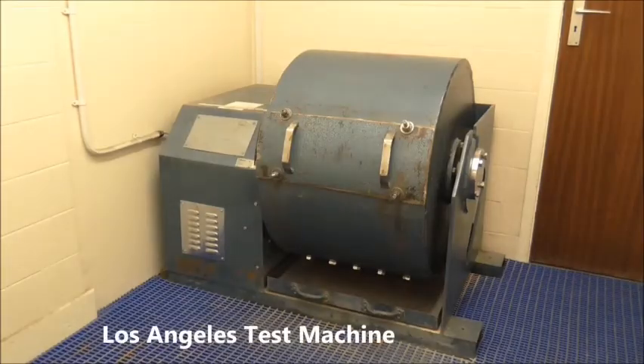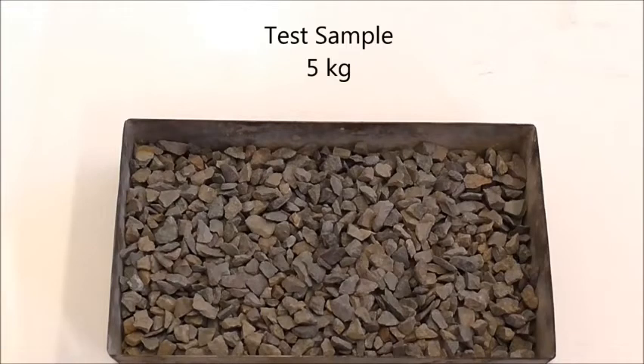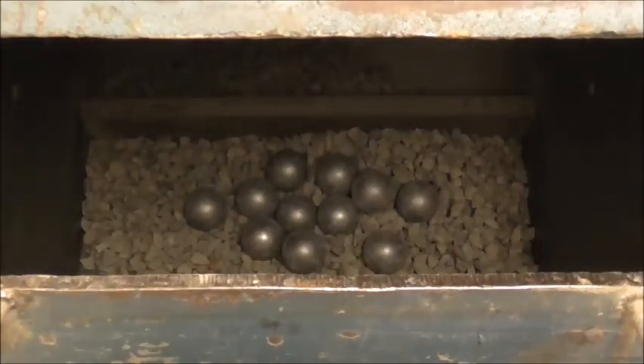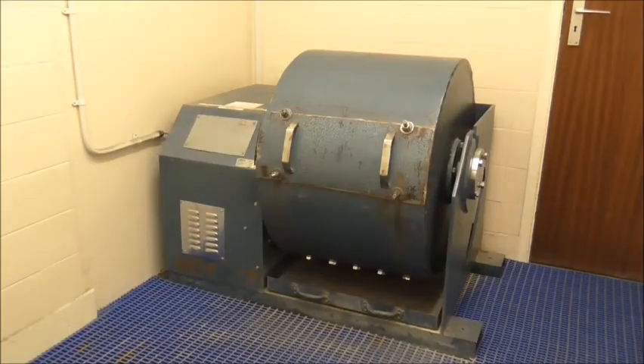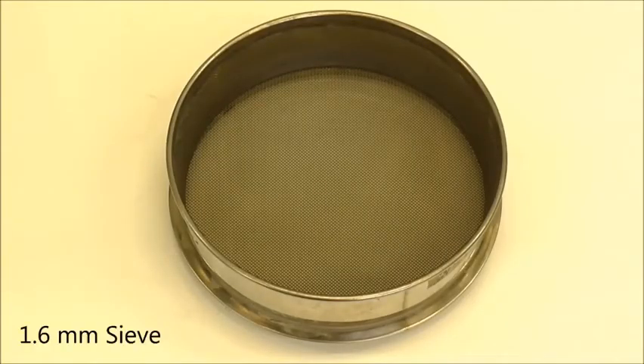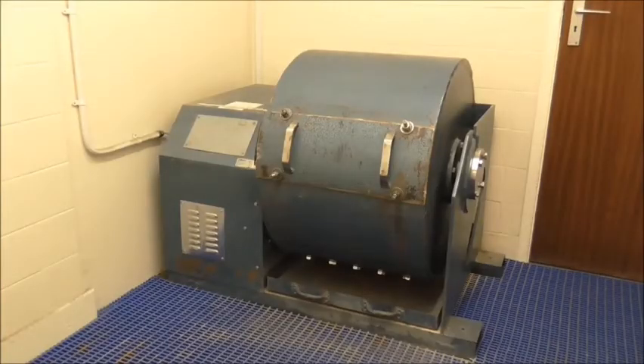The principle of the test is quite simple. A 5 kilogram sample of 10 to 14 millimeter sized aggregate is placed in a rotating drum along with 11 steel balls. The drum is then set to rotate for 500 revolutions, after which the degree of degradation is measured by using a 1.6 millimeter sieve. The more material that passes through the sieve, the less resistant the aggregate is to fragmentation. Now let's take a look at the test in more detail, starting with sample preparation.